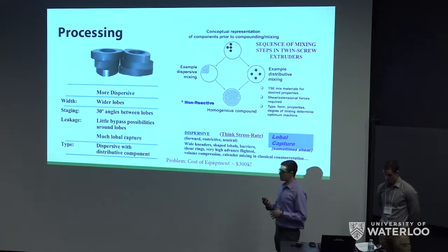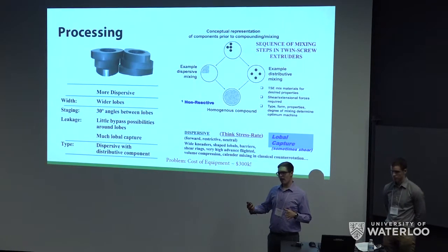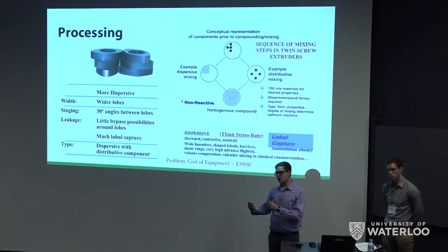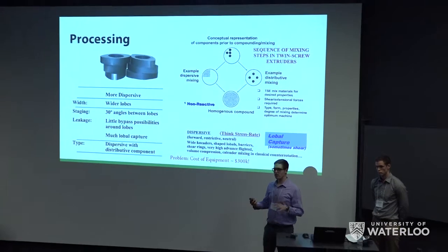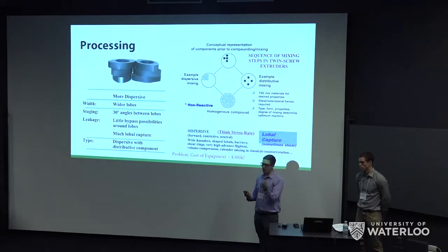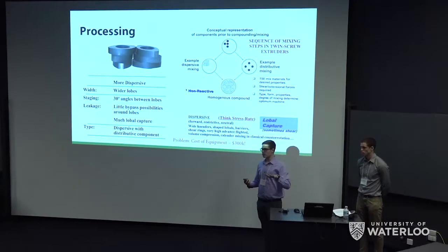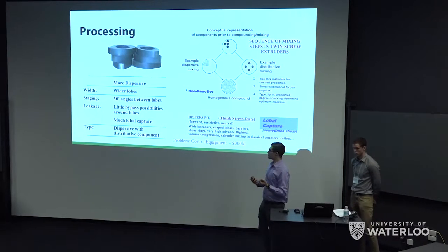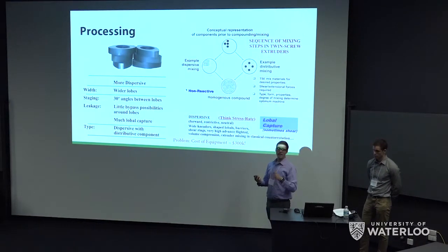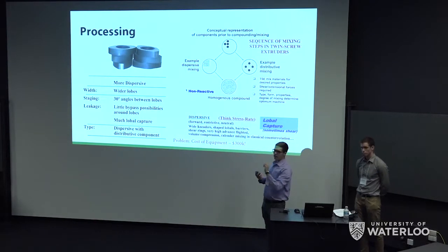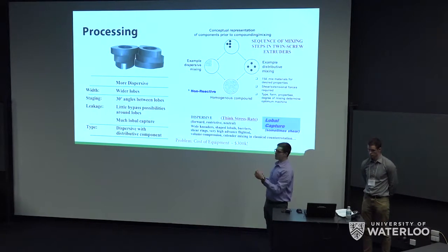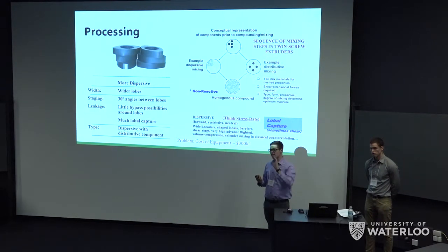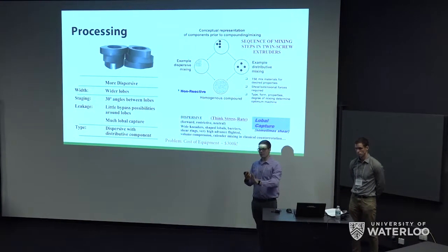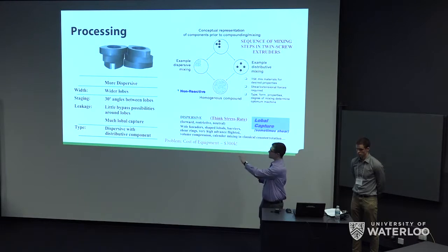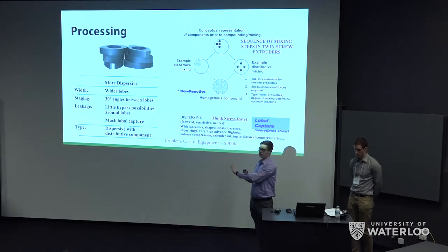is processing. So in our lab, we have a twin screw extruder that really prioritizes movement of material forward and also the distribution of material. And so if you look at the films on your desk, you'll see that our particles are very well distributed within the film, but they're not dispersed. And so what we would need to do that is an extruder that has wider lobes that does not prioritize moving the material forward. So what this allows is more shear to be pushed at the edges, and because there's less forward motion, the material would stay in there for longer. And so hopefully this type of extruder would allow us to create a more homogeneous film.